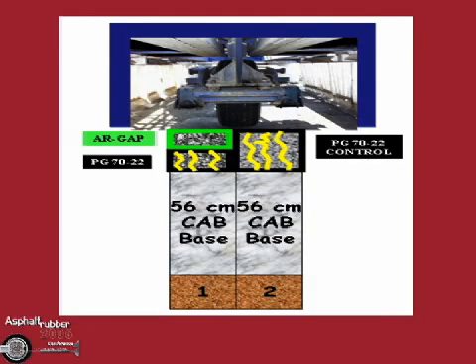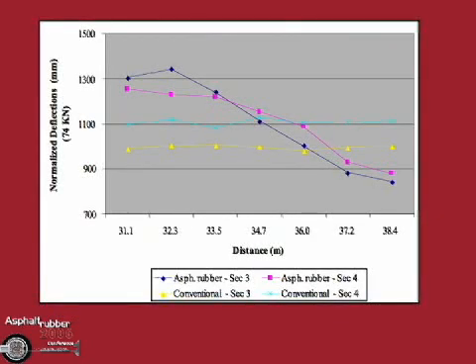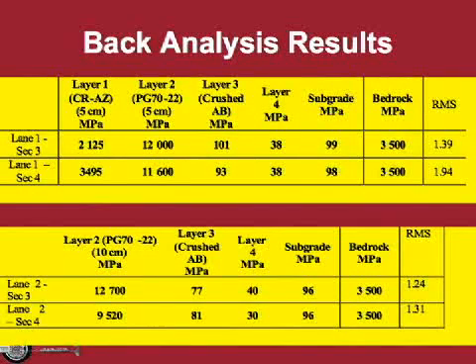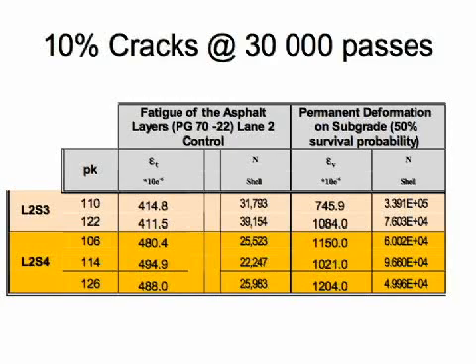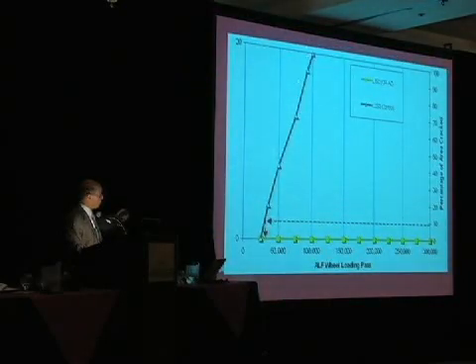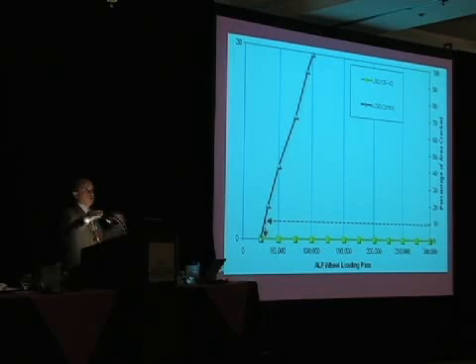Now, we took the time, and FHWA was very gracious and sent us all the FWD data, all the data that they could, and we did the back analysis, and we calculated the moduli of all the layers, using Shell. This can be done using Asphalt Institute or any normal method, but Shell worked well. Using the data that they sent us, we predicted that the different sections, well, there's some variability, some would fail after 22,000 cycles, some 35,000 cycles, and for 10% cracks, the reality is that it failed in 30,000 cycles. So we were able to predict how this section behaved very well. Meaning, up to today, researchers and engineers particularly have done a good job. The models we have can predict what happened at ALF.